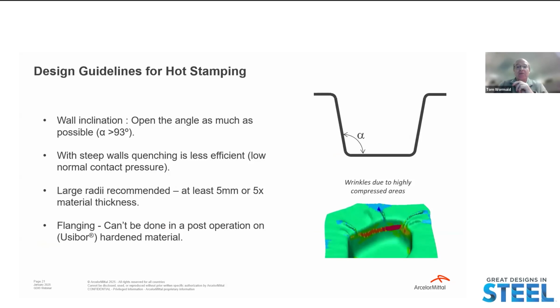Many design guidelines for PHS parts emanate from the need to have good tool to blank contact and quenching. A minimum 3-degree draft angle is recommended, with steep walls making quenching less efficient due to the reduction in contact pressure. Large radii are recommended, the standard recommendation being to keep a minimum of 5 millimeter radius. And as subsequent flanging operations are not possible for the high-strength PHS grades such as Usibor, those same flange features can often be designed right into the draw geometry themselves.